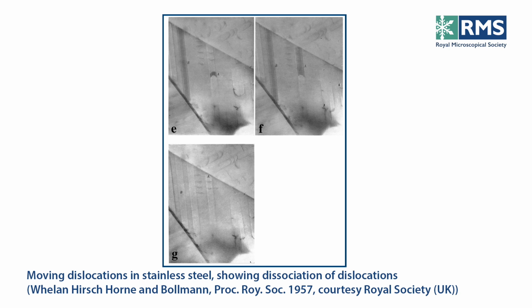Well, in fact, Bollmann was extremely expert at producing beautiful specimens of stainless steel by electropolishing. And so we collaborated with him, and he produced the specimens. And the next slide shows you a series of exposures of the same area, showing the movement of dissociated dislocations in stainless steel. These fringes you see here are in fact fringes produced by stacking faults. And in the picture labeled E, in the middle of the picture, you see what is effectively a dissociated dislocation.